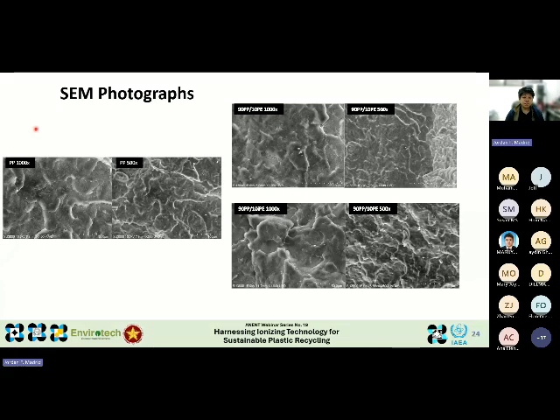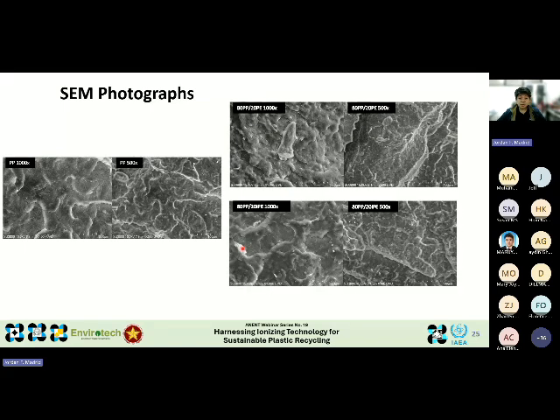We also examined the morphology of our samples by taking detailed photographs. Shown here are the scanning electron micrographs of pure polypropylene as well as the blends, 90-10 polypropylene high-density polyethylene, comparing unirradiated and irradiated samples. Aside from 90-10, we also took a look at photos of another blend, 80-20 polypropylene high-density polyethylene, again unirradiated and irradiated.